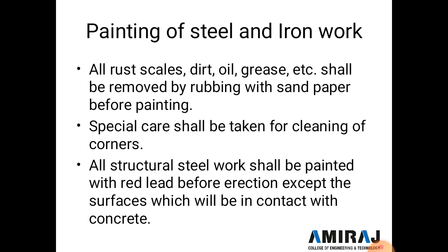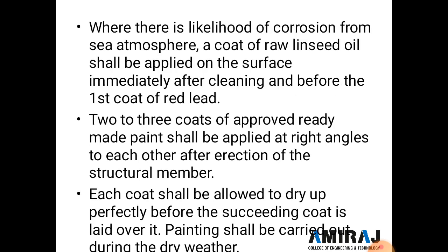All structural steelwork shall be painted with red lead before erection, except the surface which will be in contact with concrete. Where there is likelihood of corrosion from sea atmosphere, a coat of raw linseed oil shall be applied on the surface immediately after cleaning, and before the first coat of red lead is applied.